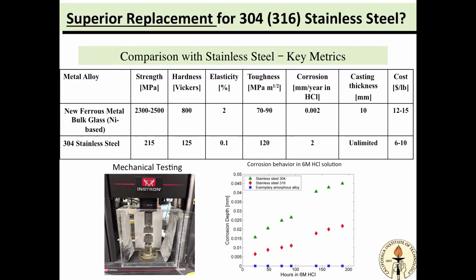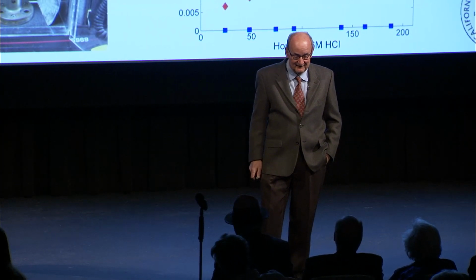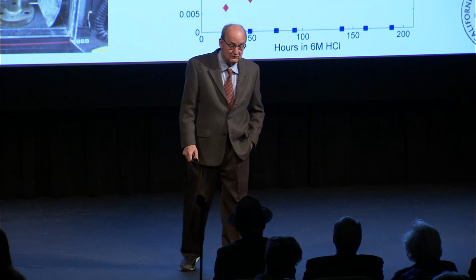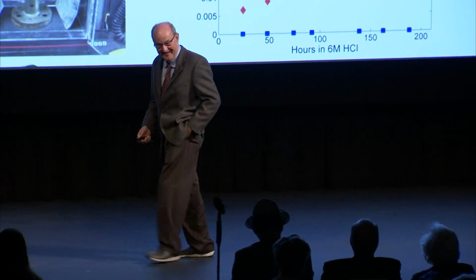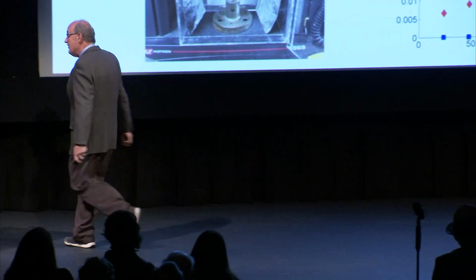So just for fun, you can put it in acid and look at how it corrodes. We use stainless steel because it's very corrosion resistant. And so we put this in hydrochloric acid for a week, and here's the rate at which the stainless steel corrodes, and we couldn't measure anything with a metallic glass. It doesn't corrode. Right? It's wonderful. Incredibly stainless. Okay?